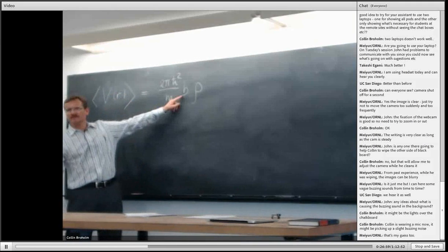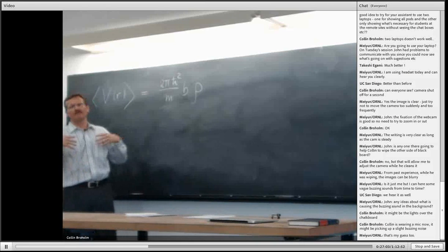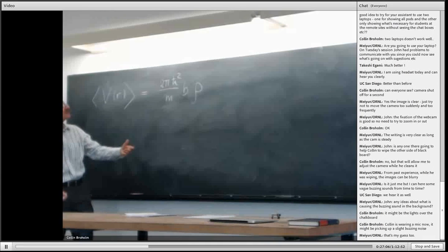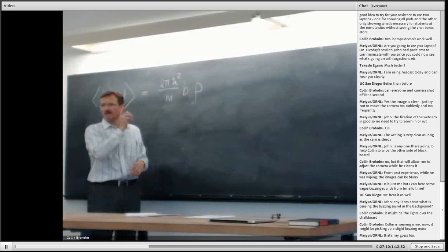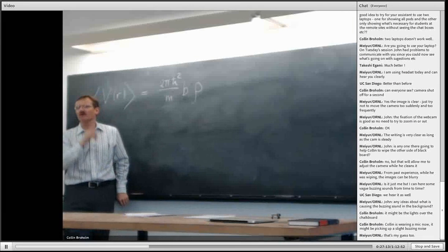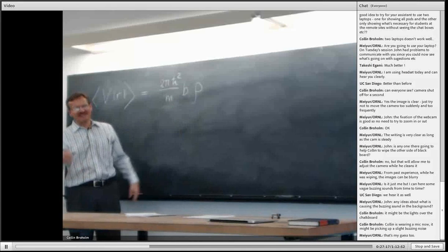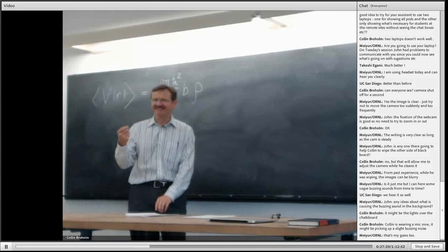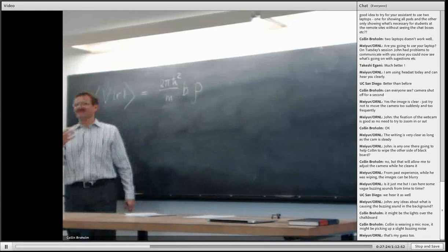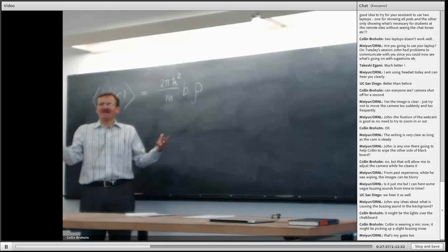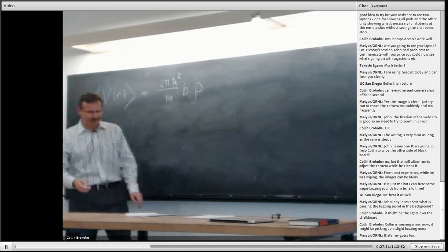If it's a positive sign, then we actually have a repulsive potential, whereas if it's an attractive sign, then we have an attractive potential. Now it turns out that with the sign convention I've used, B is generally positive for most nuclei, but not all nuclei. There are a couple of examples where this actually ends up being negative, and once again, I'm not going to be able to say exactly why that is. In fact, even Fermi started off with the opposite sign, and gradually he found that the signs were all coming out negative. Then he switched it, and from then on, we've been working in that fashion.